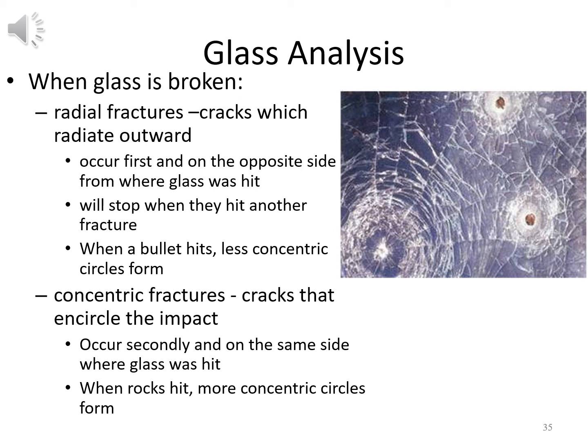So we see here some bullet holes through glass, and so when glass is broken, we get a couple types of fractures. First, the radial fractures, which are cracks that radiate outward. They occur first, and on the opposite side from where the glass was hit. They'll stop when they hit an existing fracture, so you can tell the order of shots, which shot was fired first, for instance, from our picture. This is a little complicated. We'll have an easier to interpret drawing coming up.